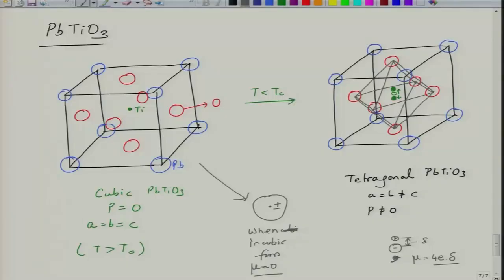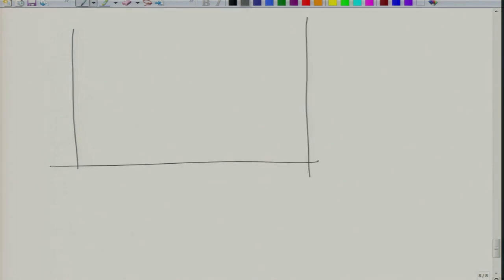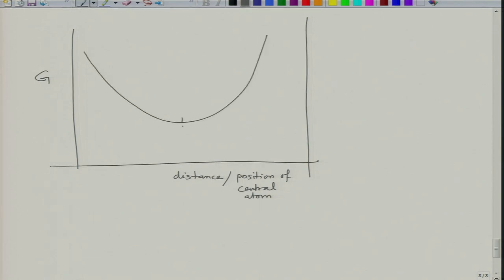So these are polar non-centrosymmetric phases which form, and this is manifested in what we call the free energy. So when you plot the free energy of such a solid, let's say we take free energy as a function of the position of the central atom. Now when it is above TC, then free energy shows a minimum at x equal to 0. x equal to 0 means center. So the titanium atom sits right here.